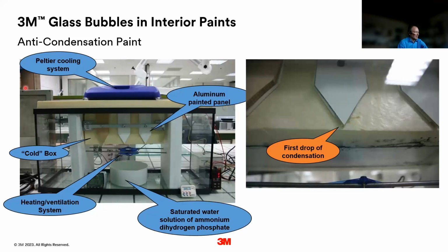That's a test setup we built in one of our labs, and it basically consists of an empty fish tank. In this fish tank, we have some salts that generate a high humidity. And we also have in this tank a cold box. This cold box was built of EPS boards, and it is cooled with a Peltier cooling system, actually just taken from a camping box. There are some windows in this cold box, which you cannot see right now. And in front of these windows in the insulation, we installed the samples.